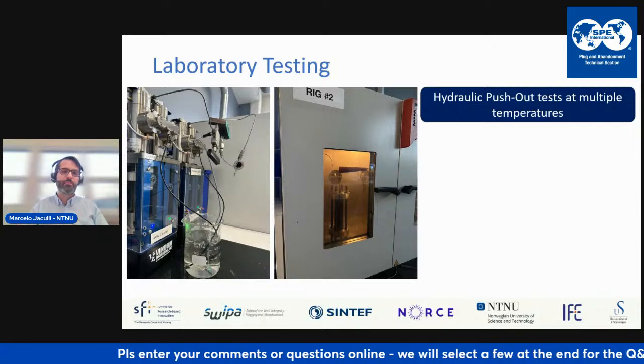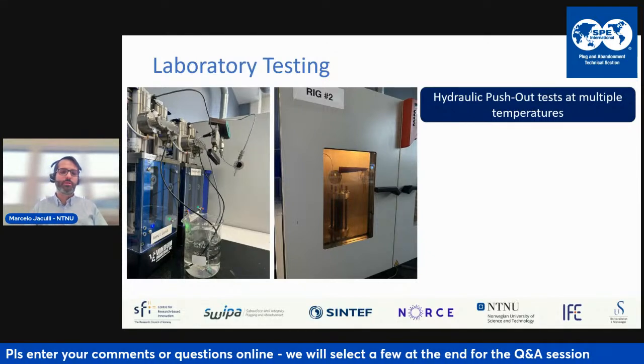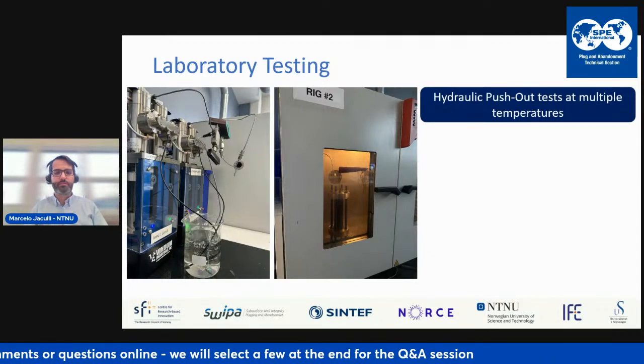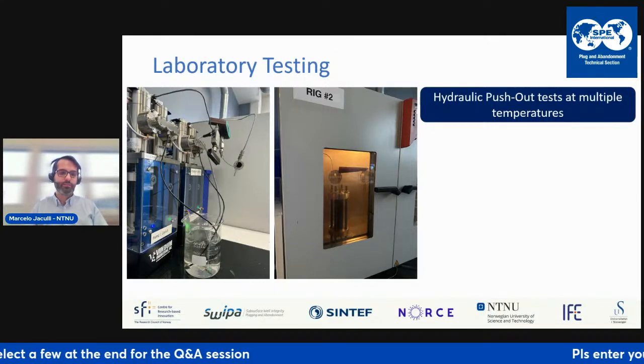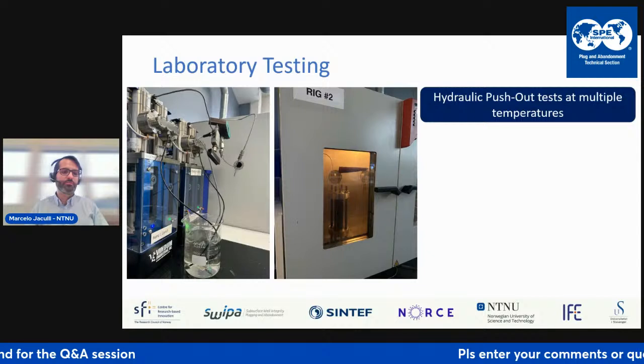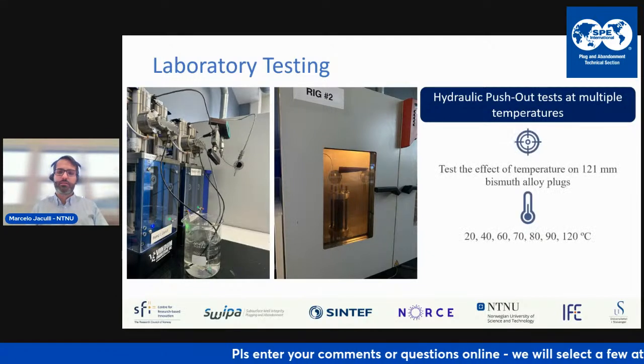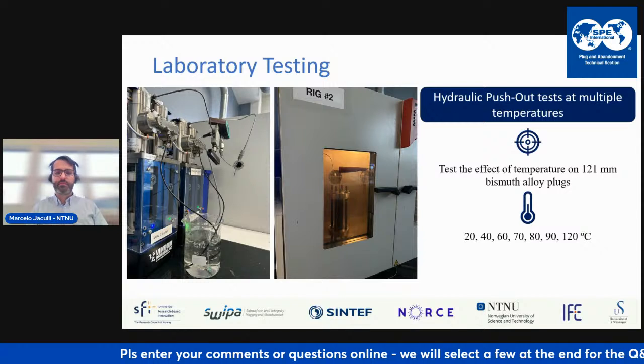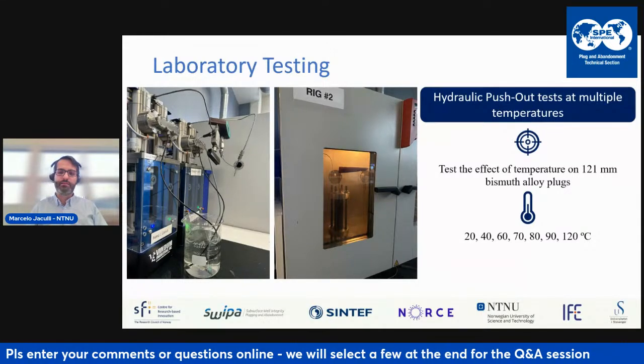By being displaced, it could mean simply that it lost its sealability capacity. You see, for example, a drop in pressure being measured, which means there's probably some leakage around the plug—it means the plug has shifted position, and you can no longer trust its capability of sealing the well.